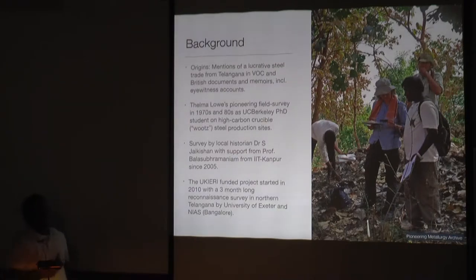And then there was not much research done until Thelma, as a UC Berkeley PhD student, surveyed a neighboring area to our research area, where she found evidence of high carbon crucible steel production, or wootz steel as it is called. And then after her, in 2005, a local historian, Dr. S. Jaikishan, with support from the late Professor Bala Subramaniam from IIT Kanpur, surveyed and recorded some sites, not in a systematic way, but we know the locations of where these sites were, and that basically attracted us at Exeter. I was a master's student then with Jill, and we applied for funding through UKIERI, which is a UK-India collaboration, to do an initial 3-month-long reconnaissance survey in the area to quantify what is there in terms of archaeometallurgical record.